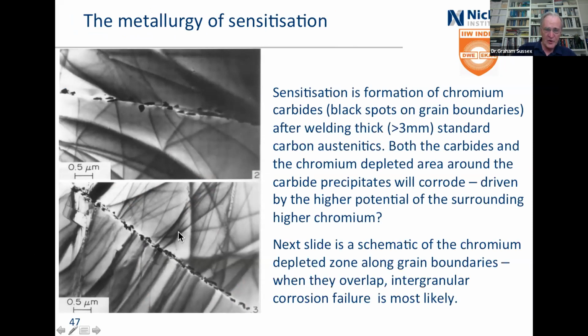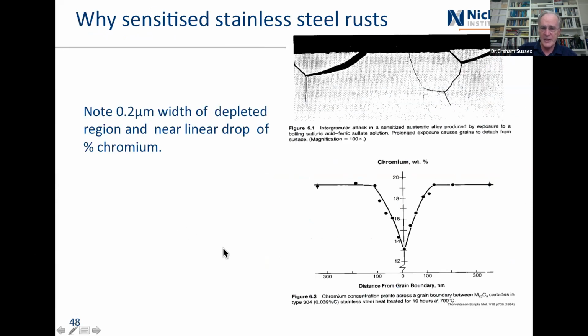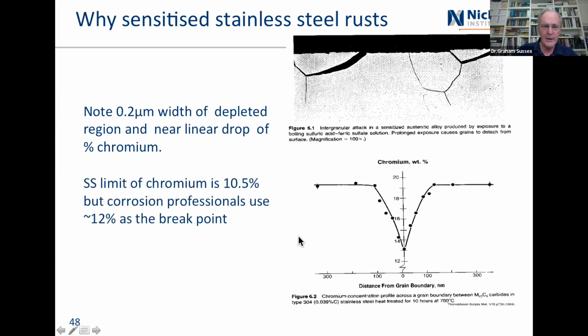The next slide shows you what it actually looks like if you go in and start looking at the chromium content either side of a grain boundary. And here we've got sort of 18, 19%. And down here, we're down to what, 13%? Okay, it's still stainless steel, inverted commas, but it's way, way down. And so either side of the grain boundary, you've got lower chromium, and so you've got a potential difference. And yes, partly it's the fact that the carbide itself isn't terribly stable, but you've also got a potential difference there. And that's 0.2 micrometer width there, so it's very narrow.